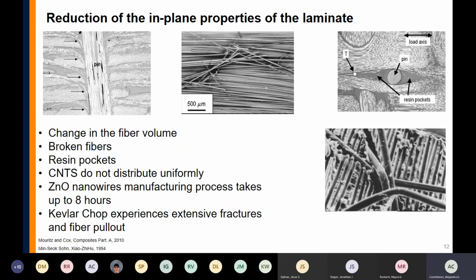Because in the case of the pin, even though, yes, they increase the through-thickness reinforcement, they will prevent the laminate from separating the two layers of fibers. There's still one problem, and that's that this pin will break your fibers as you are perforating your composite. So that will damage your in-plane properties. With the needle, it is the same. When you start using the needle and the thread, all those fibers will start breaking.